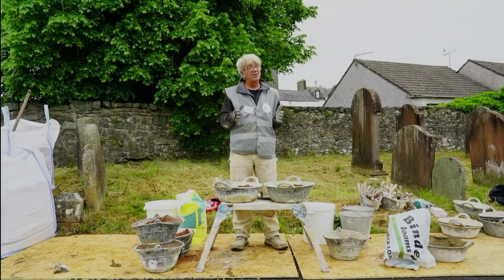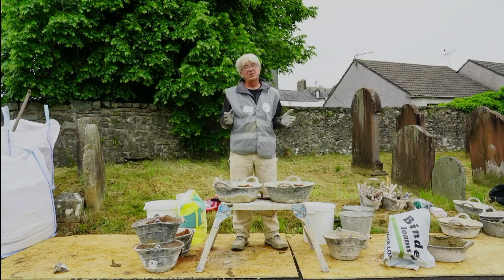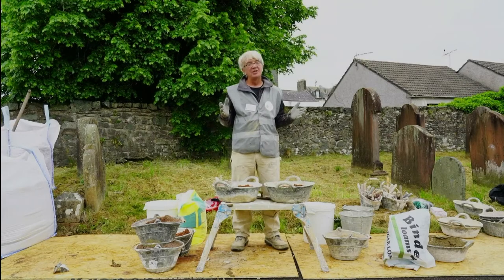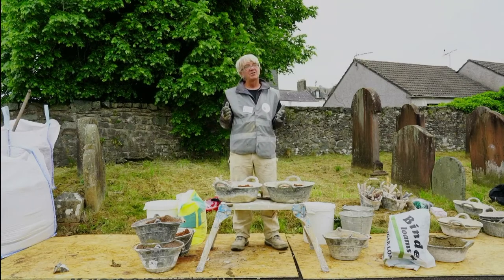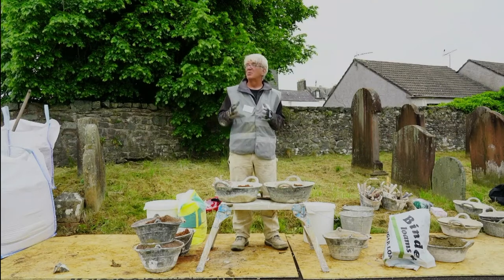But of course it was taken by the Lime Revival, who looked to the Roman example. All I can say to you is that every Roman mortar I've seen analysed comes back as having been mixed at one quicklime to three, or one quicklime to two in its proportions.